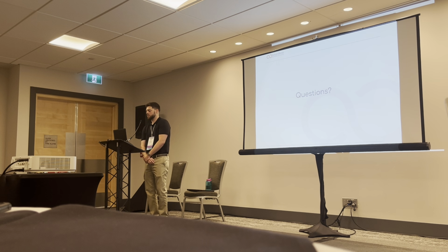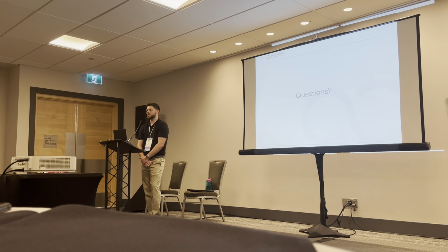Yeah, so the 3D printed materials, as far as adjustability, we mostly prototype with PA12. As far as adjustments with heating and flaring out different areas, it's pretty welcoming of those adjustments. It does change the mechanical properties a little bit. Again, very little literature on what those changes actually are. The TPU, however, is not great for adjusting afterwards. If you heat it up, it tends to kind of just flare and break.